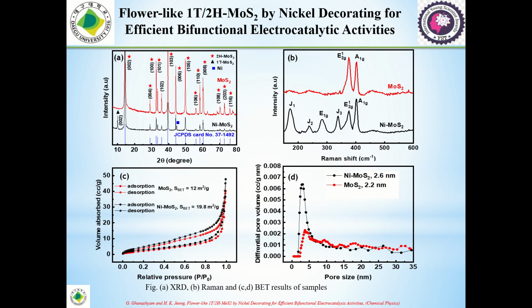And we further characterized the synthesized material by using different types of techniques. Figure A shows the XRD, using an X-ray diffractometer, and we can clearly see after nickel doping additional peaks show, which means a different phase, changed from 2H to 1T. The second figure shows the Raman spectroscopy. Additional peaks appear after nickel doping, which also supports that the phase has changed. Figure C is the BET measurement to find the surface area, which increased after nickel doping. And figure D shows the porous structure of the materials, where the pore size has increased after nickel doping.